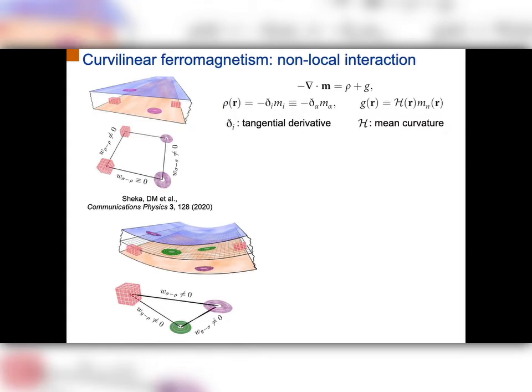Denis Sheka proposed to use the language of covariant derivatives to describe the physics in this material, and in order to better understand what is happening due to non-local interactions, he introduced the concept of three magnetostatic charges, where the conventional volume magnetostatic charge is now split into tangential charge and the geometrical charge. The geometrical charge depends on the mean curvature and on the normal component of magnetization. So basically you need a texture which has an out-of-plane component of magnetization, so that this magnetostatic charge is actually active.